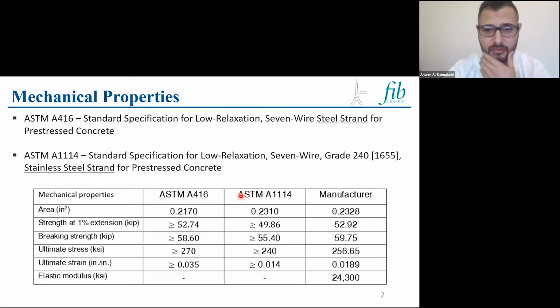We can see here that the stainless steel strands have a slightly higher area, but lower strength at 1% extension and lower breaking strength. The ultimate stress is lower, 240 compared to 270 KSI, and the ultimate strain here is 0.014, while for the carbon steel it is 0.035. The stainless steel strands that we used in this project satisfied all the requirements specified by ASTM A1114. And if you look at the ductility, it was higher than the required value.